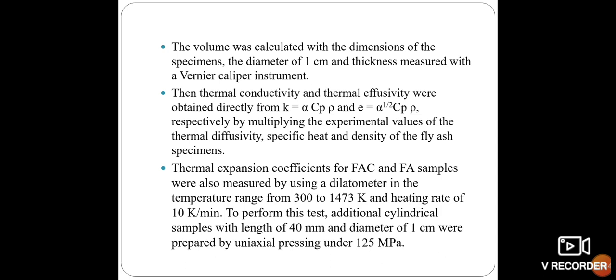The thermal expansion coefficients for the FAC and FA samples were also measured by using the dilatometer in a temperature range from 300 to 1473 Kelvin and heating rate of 10 K per minute. To perform this test, additional cylindrical samples with length of 40 mm and diameter of 1 cm were prepared by uniaxial pressure under 125 MPa.